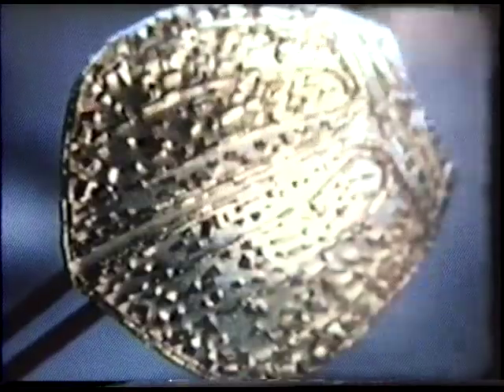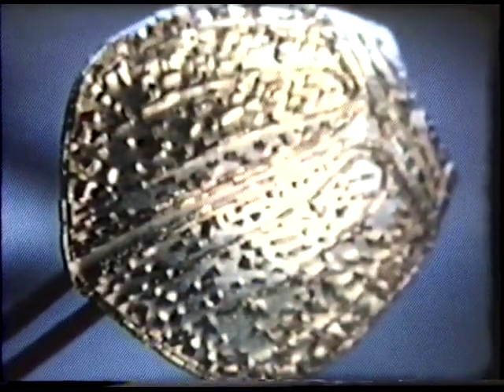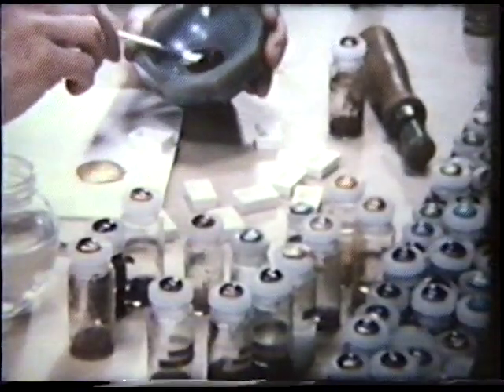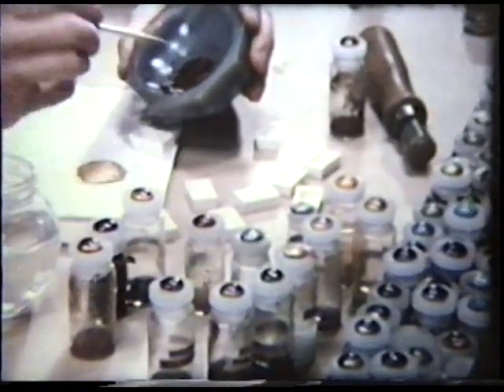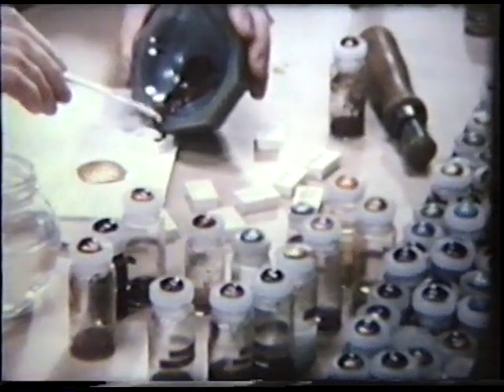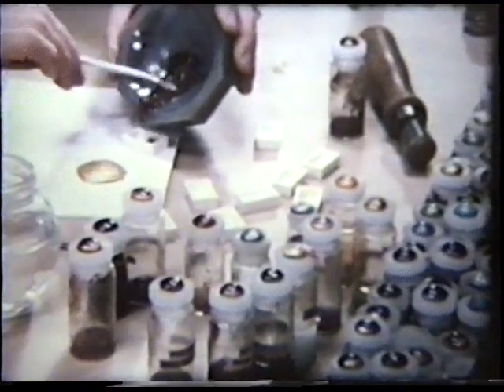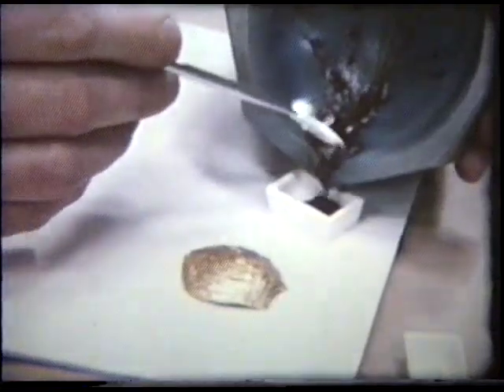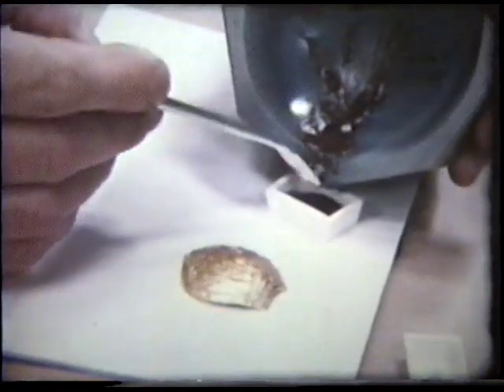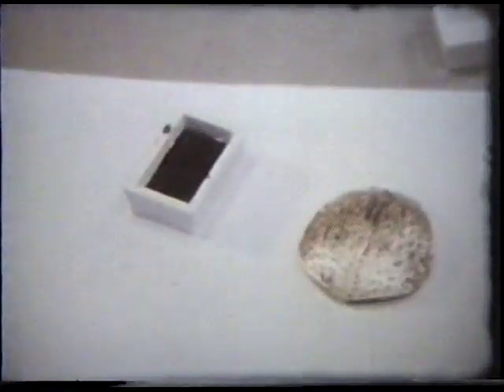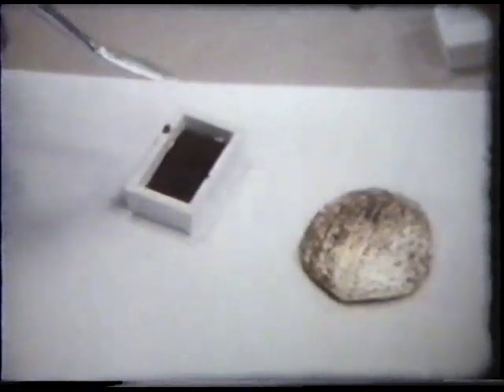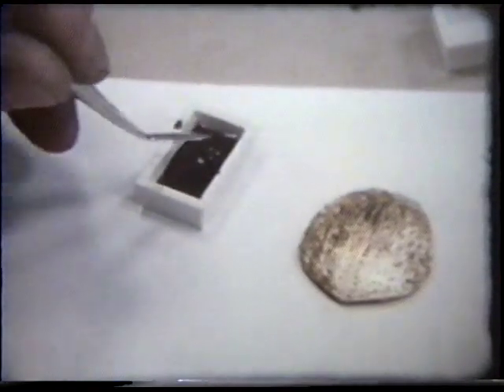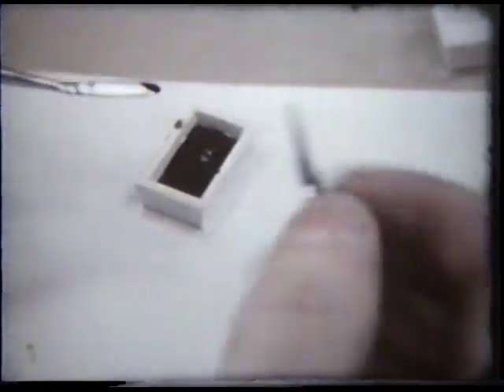The underside of the piece has been counter-enameled, and the piece is now flame cleaned to provide a greaseless surface. The first enamel to be applied has been ground to a fine powder with a mortar and pestle using distilled water. Vitreous enamel is similar to ground glass in its raw state. It is applied to a metal surface and heated in a kiln to its melting point, which causes it to fuse to the surface of the metal as a smooth, glassy covering, which may be opaque or transparent or translucent.